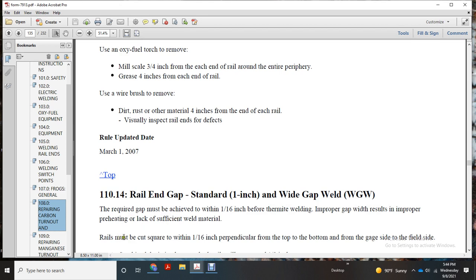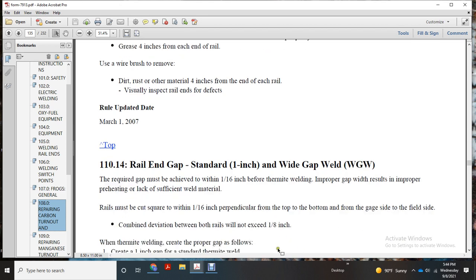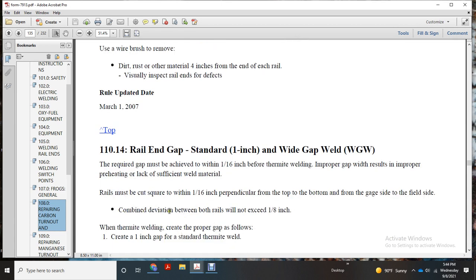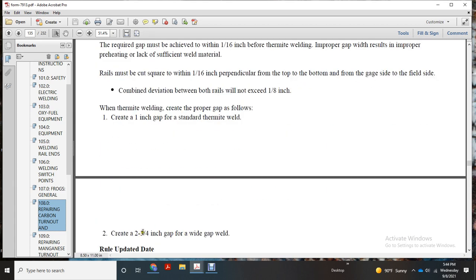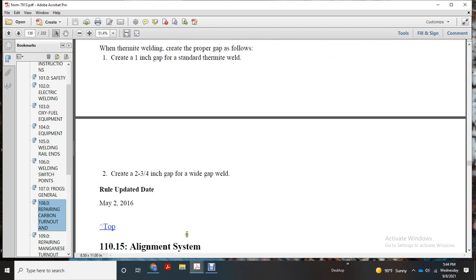The rails must be cut square, within 1/16 of an inch perpendicular, from the top to the bottom, from the gauge side to the field side. Combined deviation between both rails will not exceed 1/8 of an inch for thermite welding. Create the proper gap: a 1 inch gap for a standard thermite weld, and a 2 3/4 inch gap for a wide gap weld.